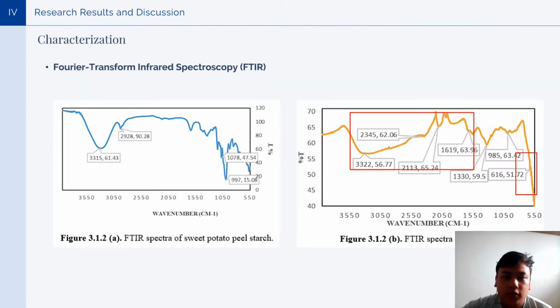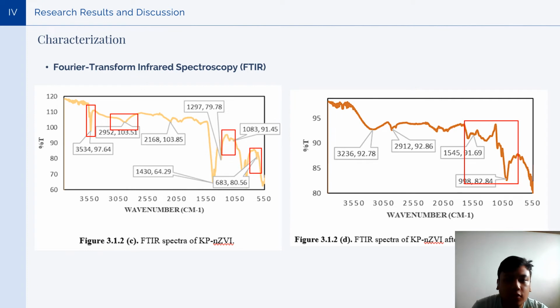An FTIR was used to determine the various functional groups and chemical bonds present in the sweet potato peel starch, the bare nZVI, KP-nZVI, and the KP-nZVI after the batch reaction. The broad bands at 3322 and 1619 per centimeter in figure 3.1.2b represent the OH stretching and bending vibration caused by the adsorption of H2O on the surface of the nanoparticle. This implies that a layer of ferric oxyhydroxide was formed on the surface of the bare nZVI. The band at 616 per centimeter denotes the symmetric stretch of Fe-O. The encapsulation of nZVI using sweet potato peel starch added vibration bands and sharper peaks compared to bare nZVI.